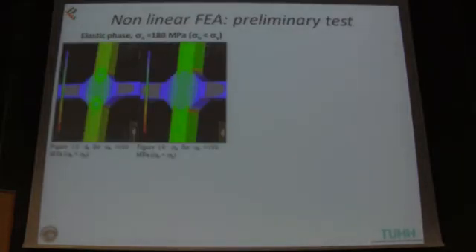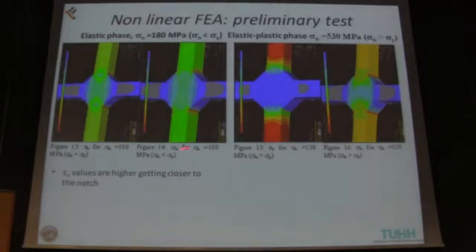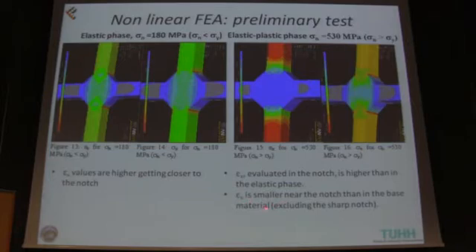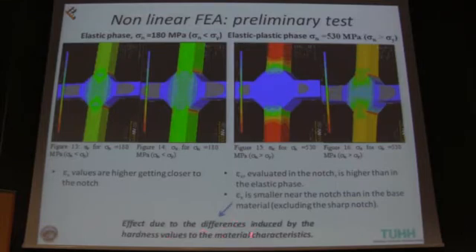A preliminary analysis was performed. First, in the elastic phase, it was observed that the strain in the vertical direction is higher close to the notch. While in the elastic-plastic phase, so for a nominal stress greater than the yielding stress, we see that the strain in the X direction evaluated in the notch is higher than in the elastic phase. But we observe that it's smaller near the notch with respect to the base material. This effect is due to the differences induced by the hardness values in the material characteristics, because as we saw before, the hardness of the welds is much higher than that of the base material.